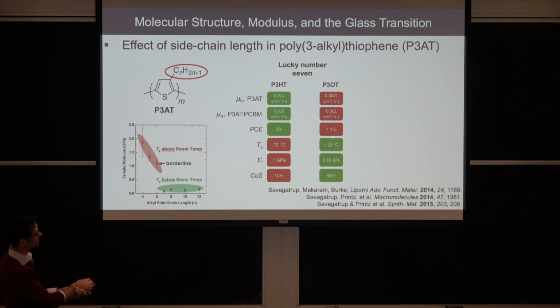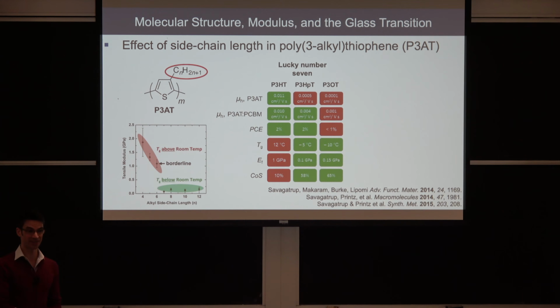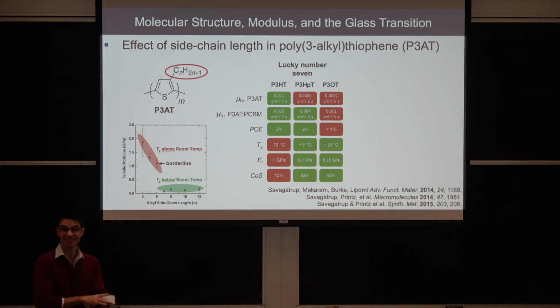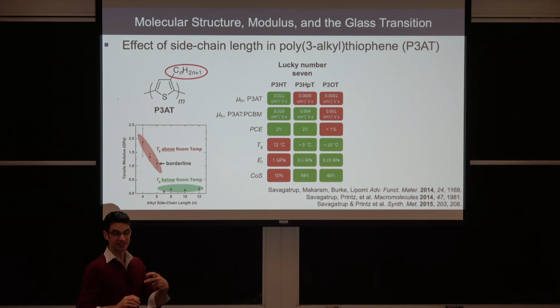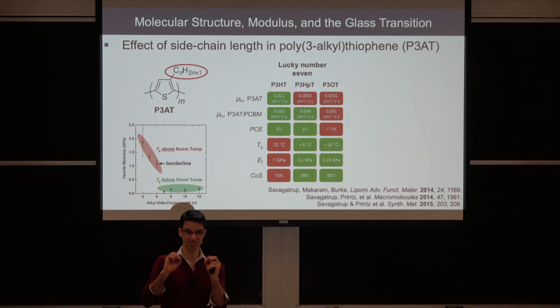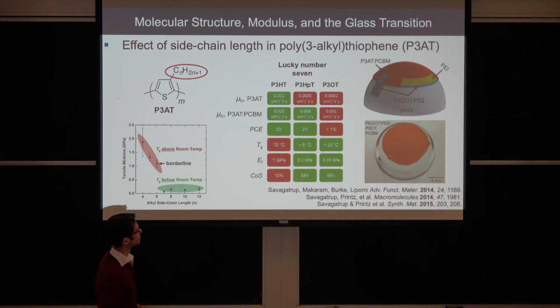Poly-3-octylthiophene has the reverse case, where the electronic properties are not so good, but the thermal and mechanical properties are favorable, so good deformability. If you look at number 7, it fulfills lots of these criteria. So just by tuning these little parameters, just this 1 carbon addition to the side chain, we can actually enable some applications that we couldn't before.